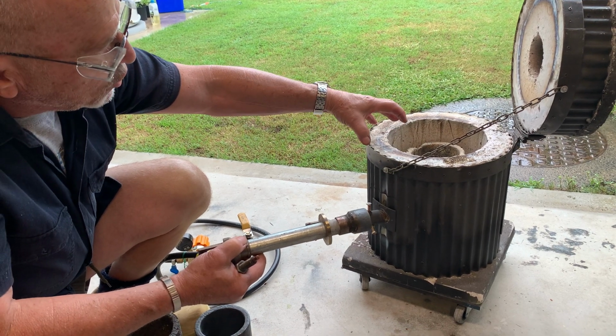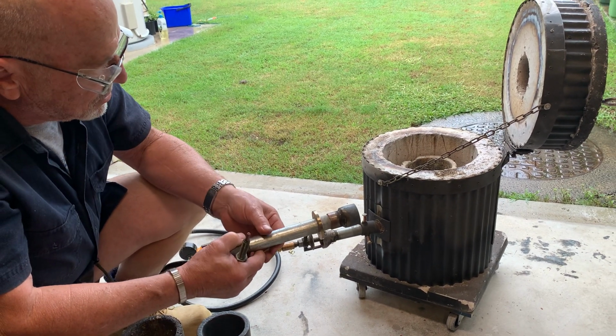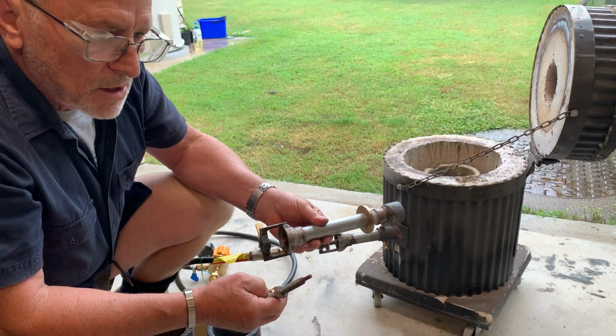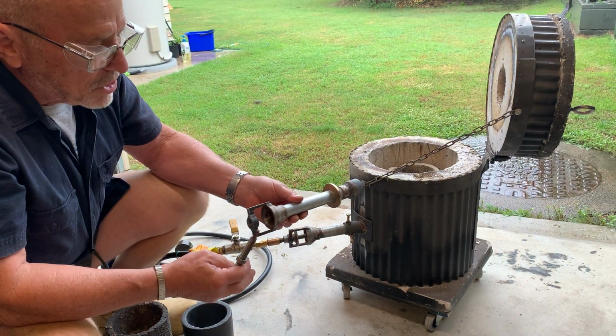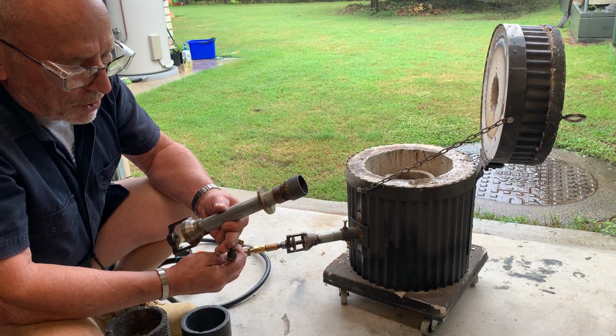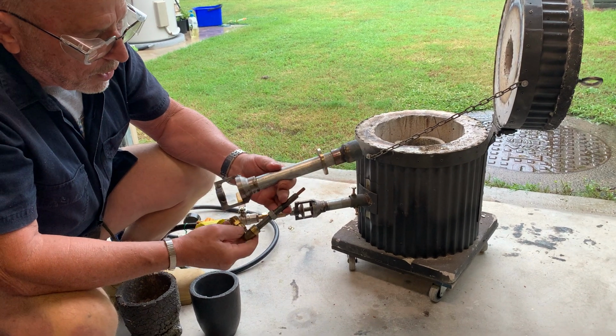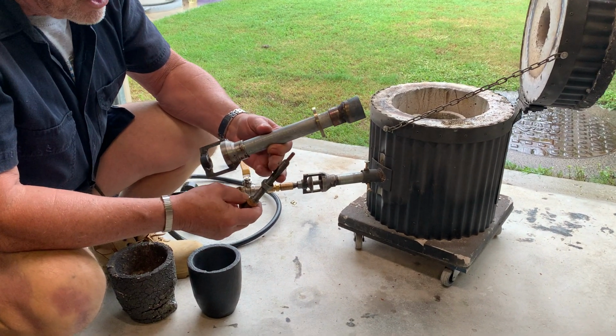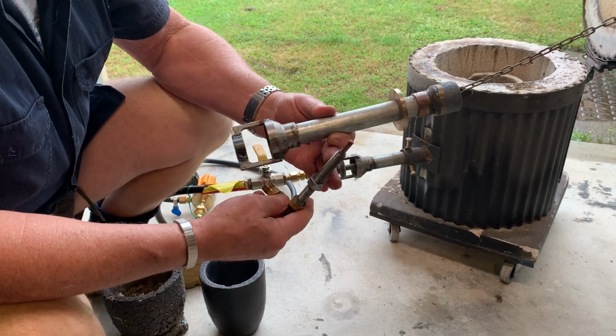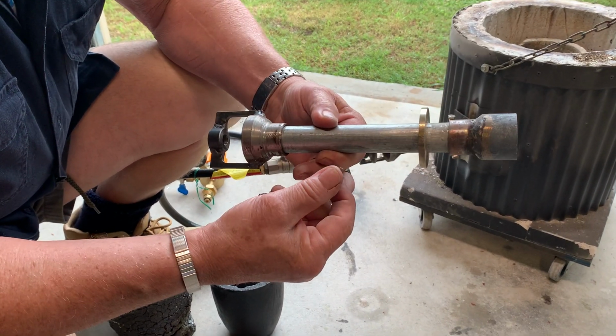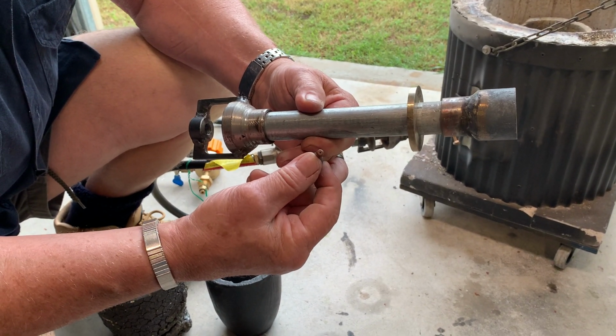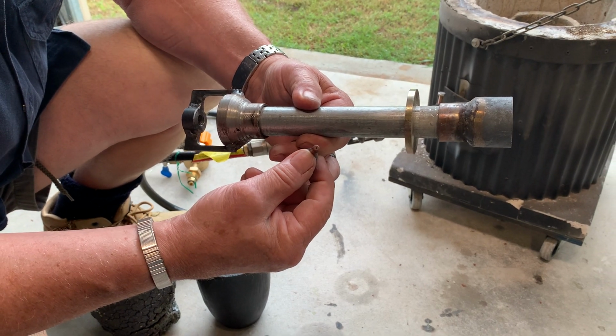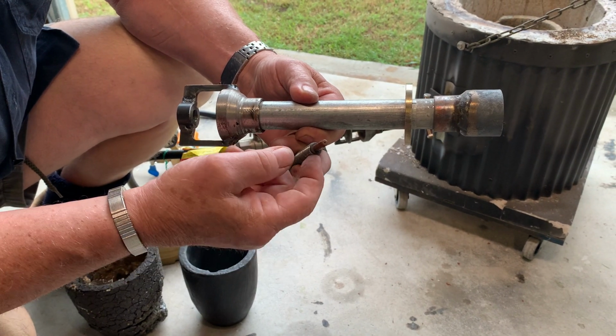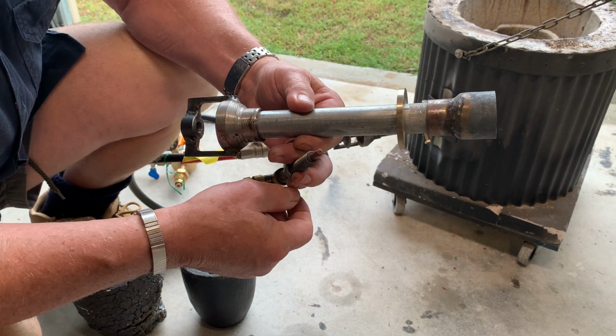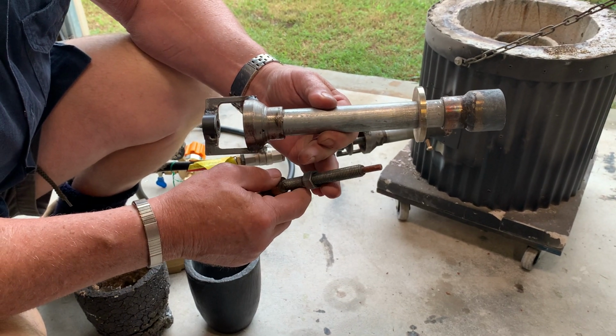If you heat it up too quick, you're going to get a lot of cracks and uneven heating. So heat your furnace up slower. And I find a 0.9mm tip really, really great. A good size, economical on gas. So you want about 1100 to 1200 degrees centigrade for melting or pouring bronze, and this size tip will actually get that temperature for you in an economical way.